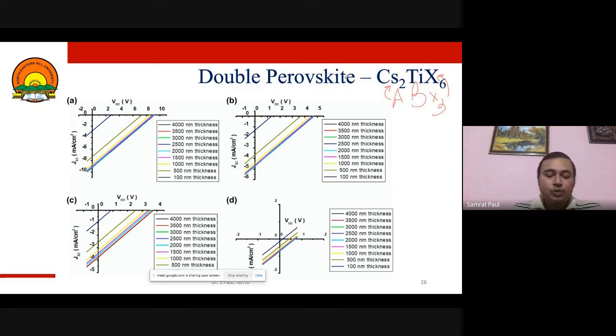But the important thing to note here is that if we are planning to have organic inorganic based double perovskite, it is not at all stable, because if we increase the amount of organic material here and fuse the two unit cells to make a new single unit cell, they become very unstable. So here only inorganic perovskites are still reported to have double perovskite. I might not know if someone has reported recently or not, but we didn't find, and we could not synthesize that type of material also, because they degrade within hours. So for double perovskite, it is a purely inorganic component.